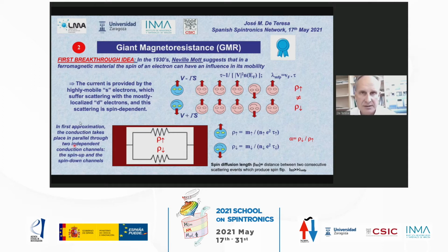So if we assume that in certain conditions, such as at low temperatures and with low mean-free paths, we have two conduction channels in parallel, the resistivity for the spin-up electrons and the spin-down resistivity for the spin-down electrons, then we can consider that the conductivity is given by these two parallel channels with this important property that the resistivity of the spin-down channel is different to that of the spin-up channel. So in this context, there is a new concept that we have to introduce, which is the spin diffusion length, which is the distance between two scattering events which produce a spin flip. Most of the scattering events will not produce a spin flip, but when it is produced, this distance is called the spin diffusion length.